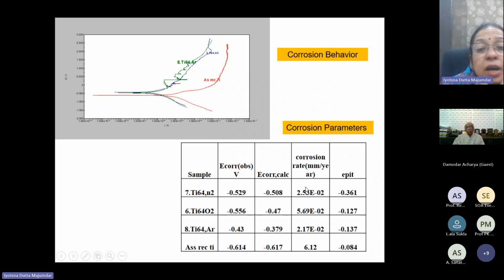But this reduction obviously is not only for the textured surface. This corrosion study was done on the surface where there were a combination of both textured and non-textured surface. So possibly area corrections were not done. Area calculation is very important in corrosion, but we just took the average surface area, while the actual area, whenever you do texturing, is much higher than the average area. So whatever corrosion rate is observed is actually a kind of composite.